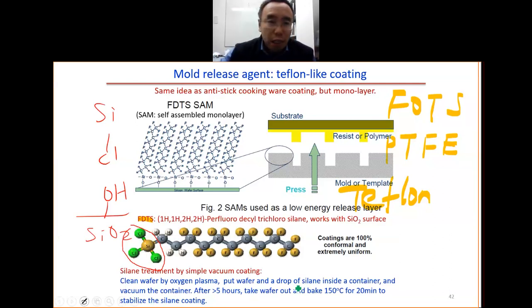So the chlorine here and this hydrogen here, they will come together to become HCl. So this one is the vapor, it's gone. So you leave behind oxygen here. So this oxygen here will be bonded to the silicon. That's why you see we have this silicon oxygen silicon bonding. So this is how you bond to the substrate. But here you also see that you have also the lateral bond. You have silicon oxygen lateral bonding.